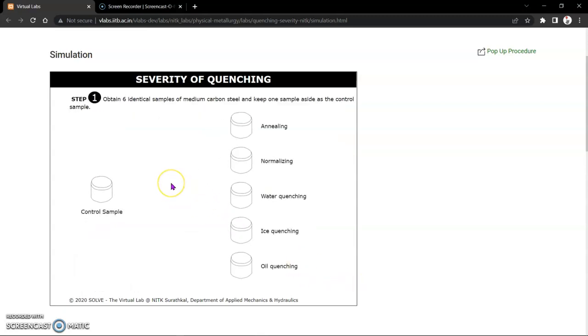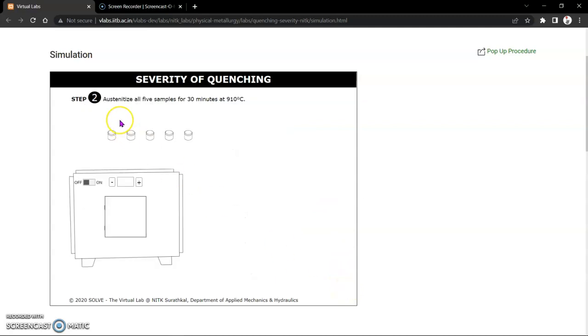Step 1. Obtain 6 identical samples of medium carbon steel and keep one sample aside as the control sample. Step 2. Austenitize all 5 samples for 30 minutes at 910 degrees. First, turn on the furnace. Set the furnace temperature to 910 degrees.